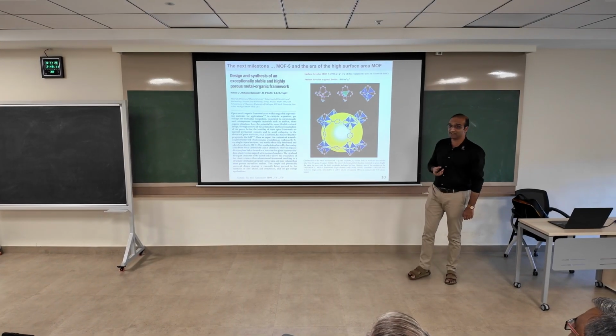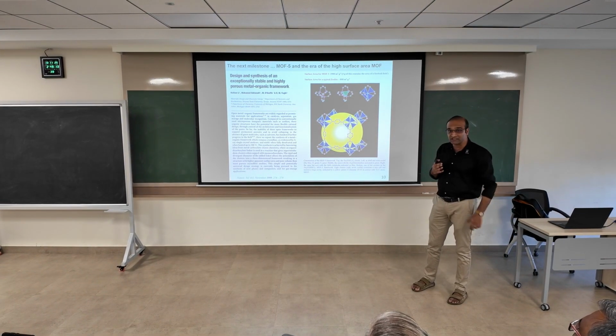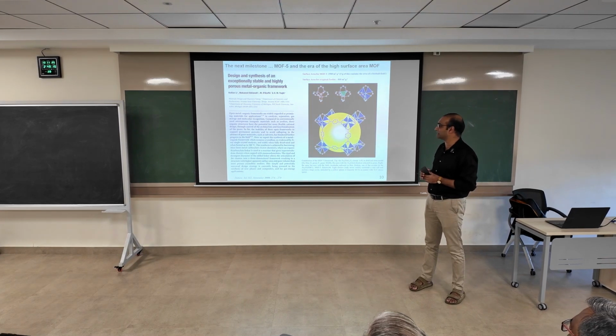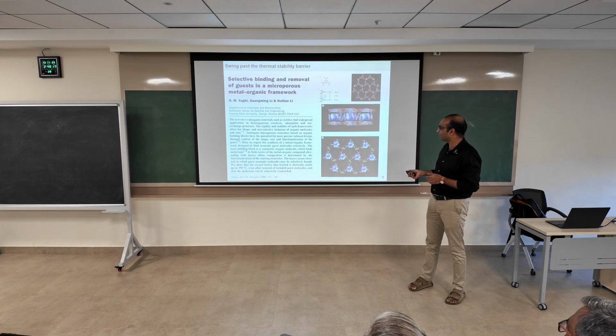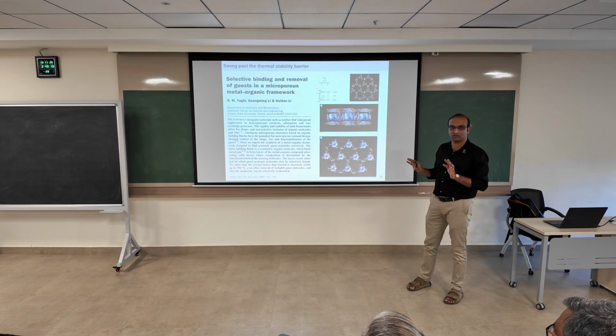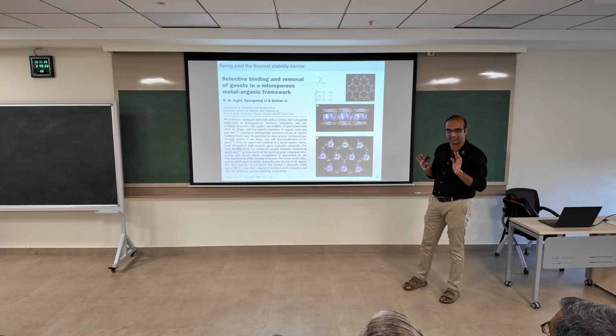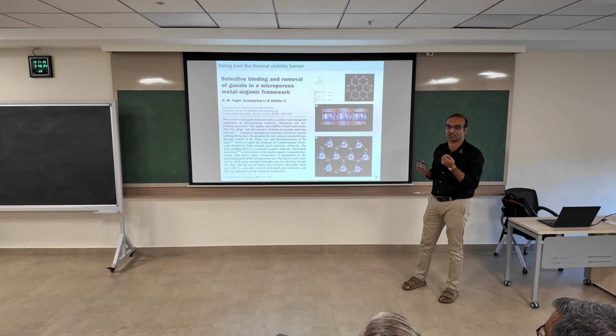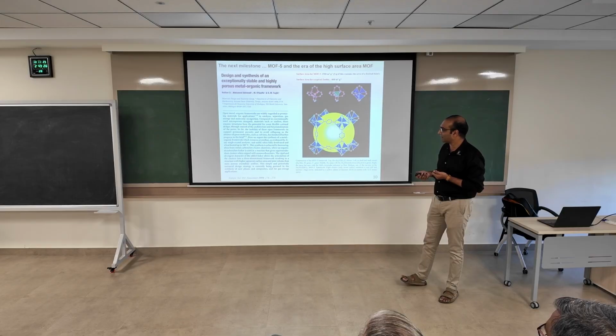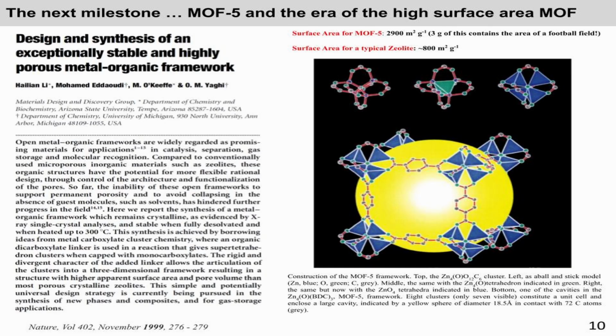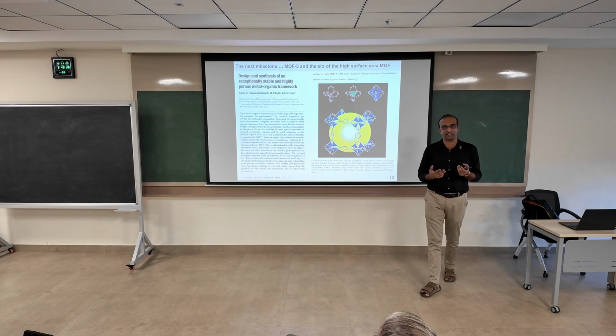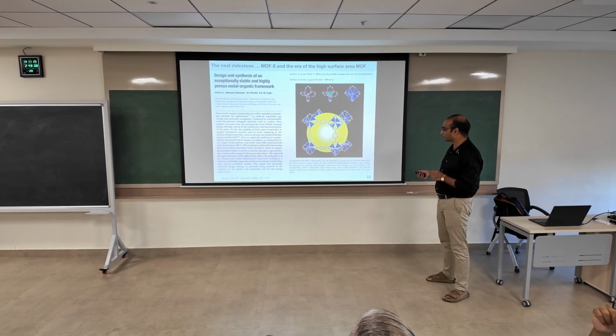Okay, so now one of the biggest problems was that all these MOFs were not very thermally stable. Even this one was somewhat not good at high temperatures, like even above 200 degrees Celsius, it would not have its structural integrity. Back then it was a big deal that it was stable up to 300 degrees Celsius. Now you have MOFs which are stable up to 600 and even 700 degrees Celsius. They are approaching the kind of stability we've seen from zeolites. But this MOF was the first one.